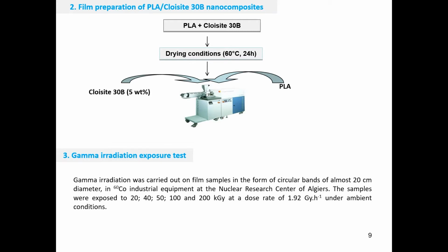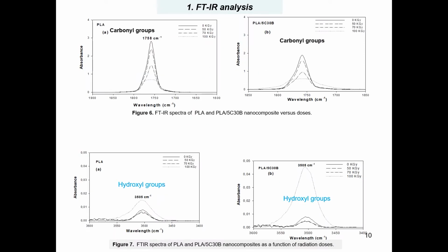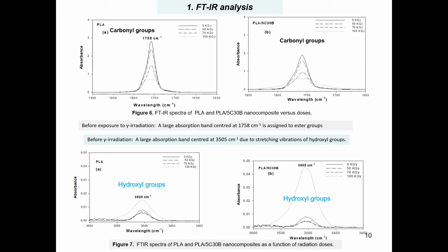And the gamma irradiation test was carried out with a cobalt-60 industrial equipment at various doses, starting from 20 to 200 kilograys at a dose rate of 1.92 grays per hour under ambient conditions. Let's start discussing now the FTIR data.